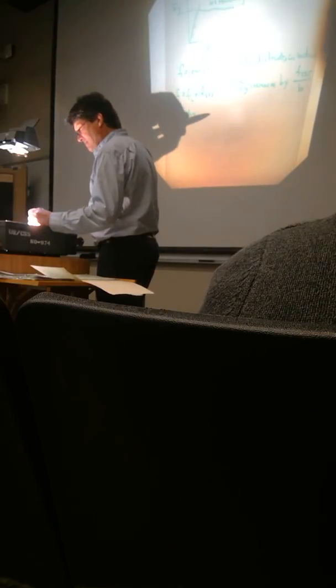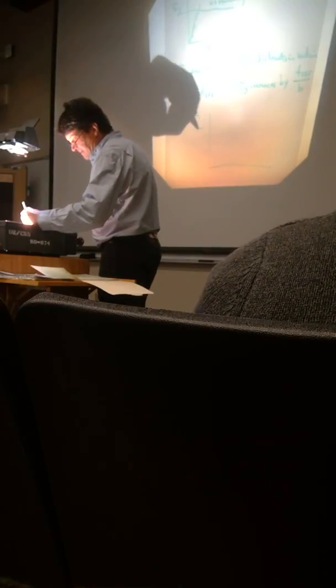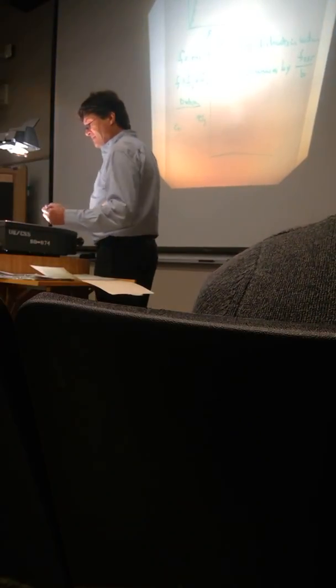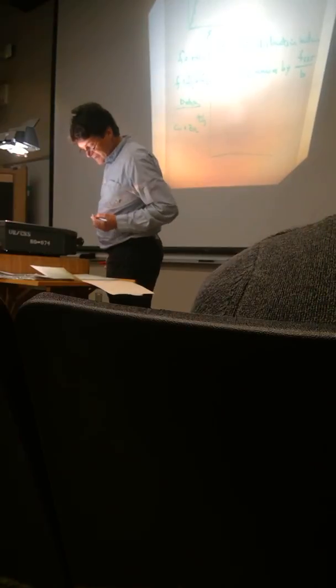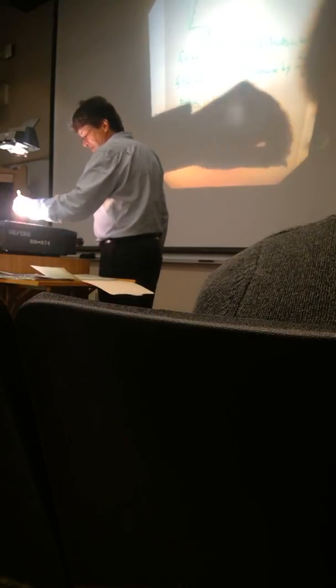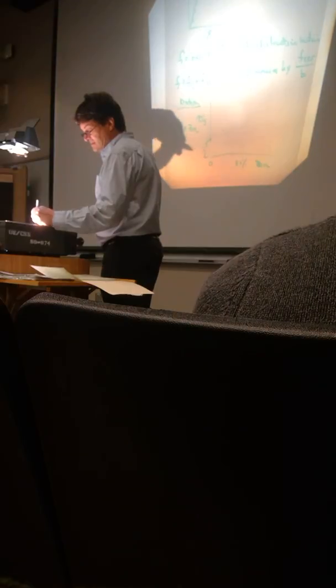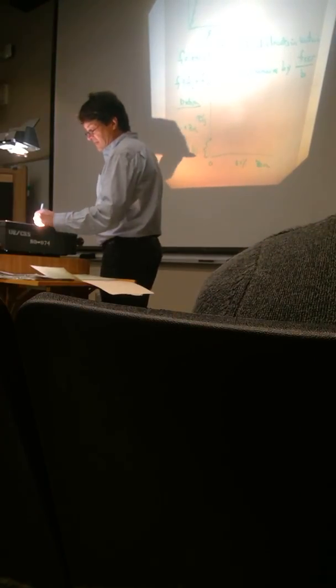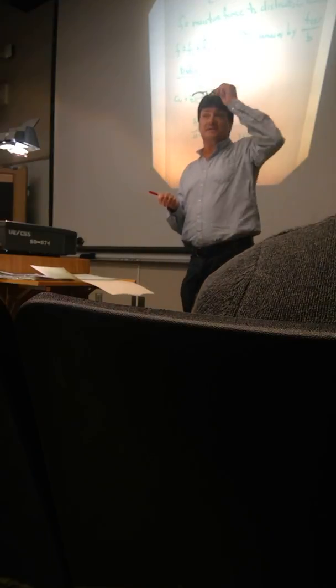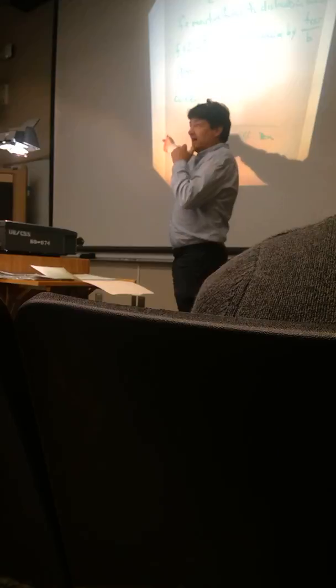So if you look at some data, and we plot tau y, let's say it's copper, and you're adding zinc, and here is 0 to 30% zinc. We know it starts at some value here. This would be F of I over B, just the intrinsic resistance to dislocation motion of pure copper, right? That's your tau y, your tau c, or your intrinsic divided by the Burgers vector.